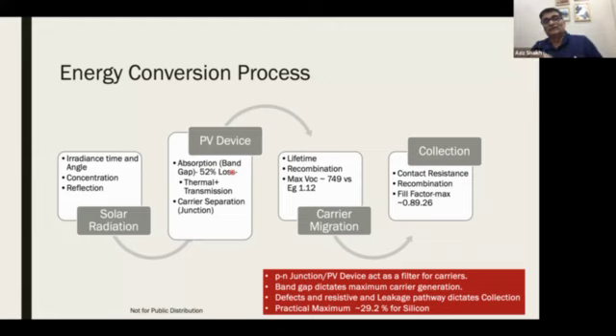Now I got a junction, which is a filter. Now I created these carriers. I got to migrate them to the right side of the polarity, and there is a voltage. This voltage is pretty much dominated by the band diagram. I'm not going to get into it, but it is dominated by the band gap and the Fermi levels and so on. Even though the band gap is 1.12 eV, the maximum voltage you can get out of a crystalline silicon solar cell is 749 millivolts. So there is a loss of voltage, which is just practical loss.